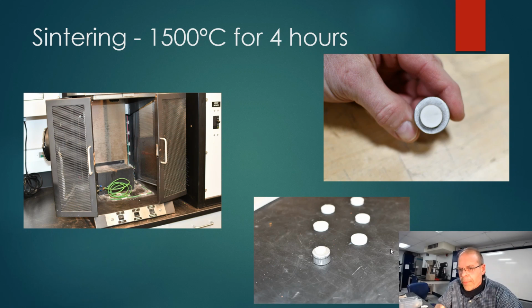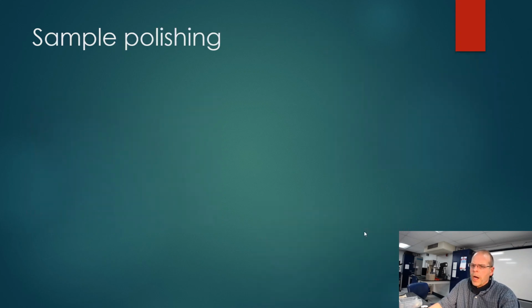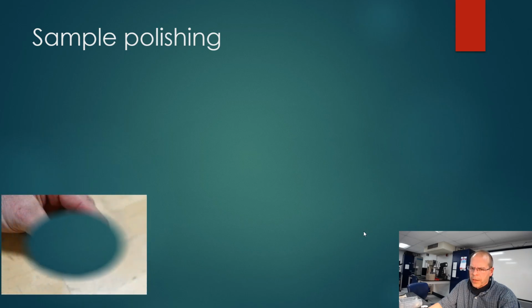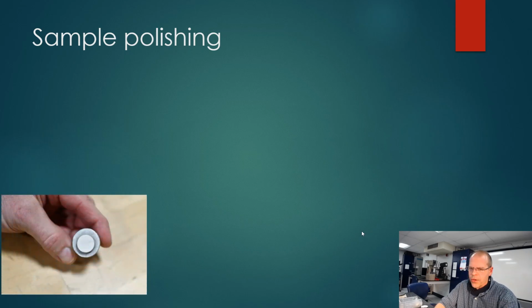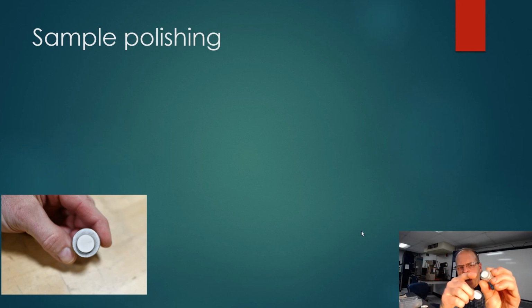Again, in a perfect world, I'd be able to heat up around 1700. Unfortunately, I don't have access to a furnace right now that can heat that much, so our samples won't look quite as crisp as those when we see the scanning electron microscope images. After 4 hours, we're going to pull these samples out. And the first thing you're going to notice is that after the 1500 degree 4 hour sintering, your sample has become a lot smaller. Again, here's our original puck. And you notice I have this glued to an aluminum puck. The reason this is glued with a substance called crystal bond is because we have to polish this, and there's just no other way to hold it.